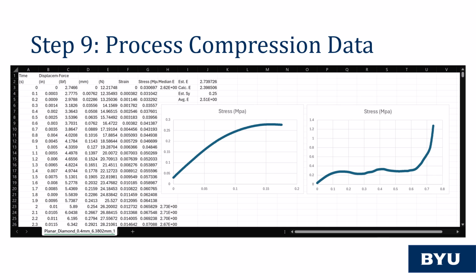The graph on the left shows the curve prior to this first yield point. This curve is used to estimate the stiffness and strength of the lattice design. The stiffness is approximated using 3 methods. First, a visual approximation is taken, then a central difference approximation is taken at 2 points in the linear region, and finally a running average is generated for the duration of the linear region from which the median stiffness is saved. These 3 methods are then averaged to give the Young's modulus of elasticity for the sample. The yield strength is estimated from 0.2% strain offset using the approximate slope of the linear region. This method of measuring the material properties was repeated for all 30 datasets.